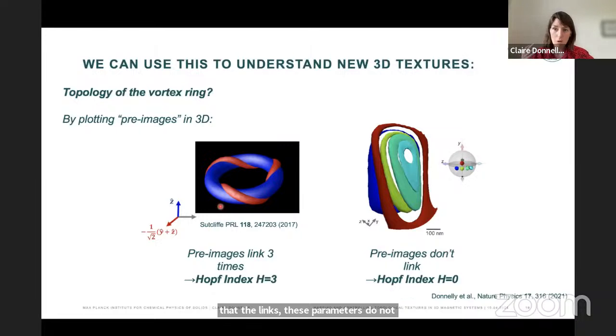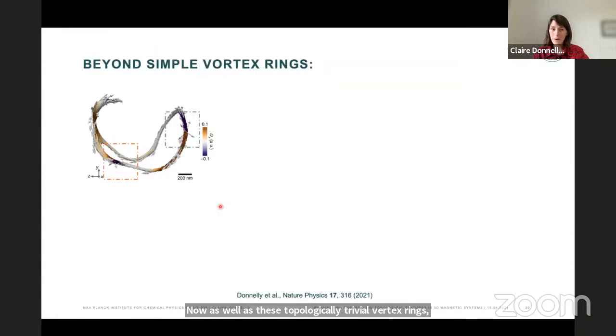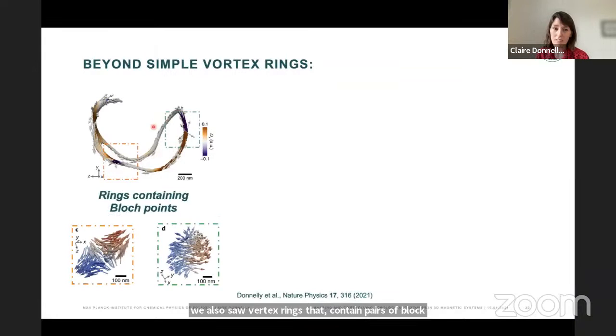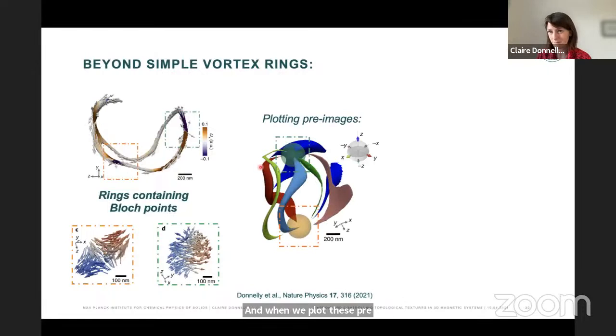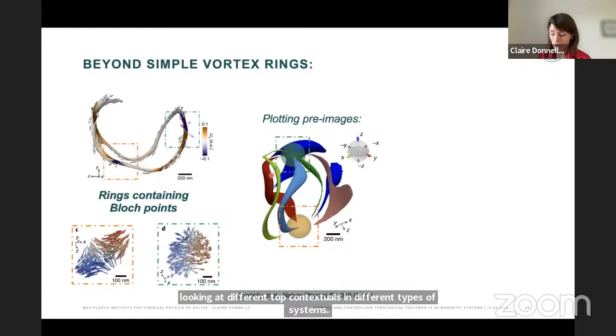But it does show that if we were to have such a non-trivial texture, so a real Hopfion texture, with such a technique, we are able to really determine that it is a Hopfion in 3 dimensions. Now, as well as these topologically trivial vortex rings, we also saw vortex rings that contain pairs of Bloch point singularities within their loop. And when we plot these pre-images, we actually see something that now looks quite familiar if we are looking at different topological textures in different types of systems. In particular, we can identify this as a magnetic toron.